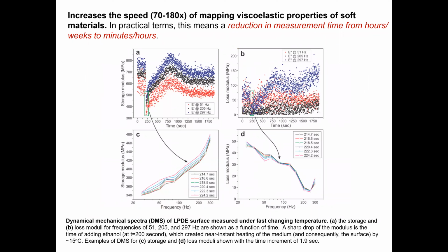Time dependence. This is where we change time. It's really noisy, but what happens here: there are 3 different frequencies, and to avoid memory effects of polymers, each point here is measured at a different location. That's why it's so noisy. What happens at this moment is that we sharply change the temperature of the liquid. We added ethanol. When you mix ethanol with water, it increases its temperature by up to 15 degrees Celsius, and then it cools back down. So you see it gets softer, and then slowly comes back, and it oscillates because you definitely have convection and so on.